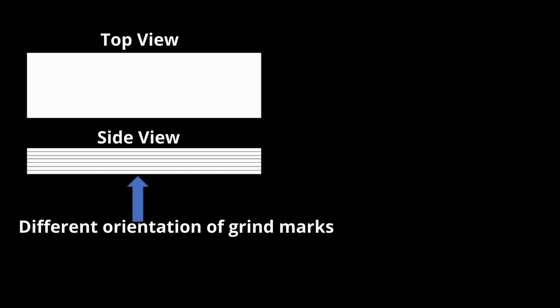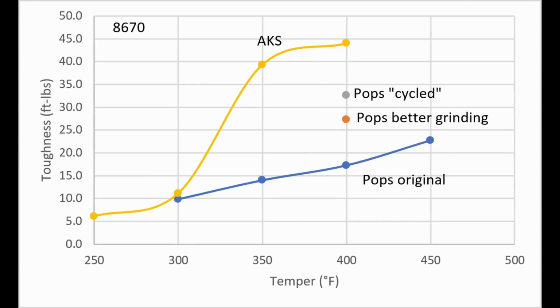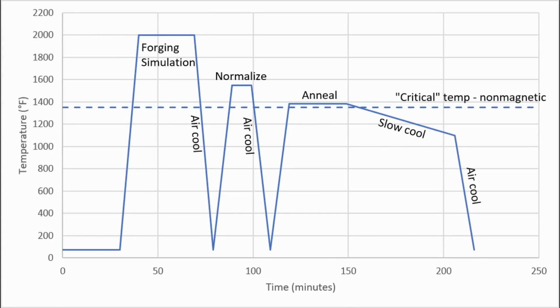So one thing I did was heat treat and machine my own specimen out of the same steel, and indeed the toughness did go up significantly, though not to the heights of the Alpha Knife Supply material. So I did yet another study on this material for this video, where I did my same thermal cycling procedure that was on the previous 15N20. This would allow us to eliminate any differences in the steel in terms of prior microstructure.